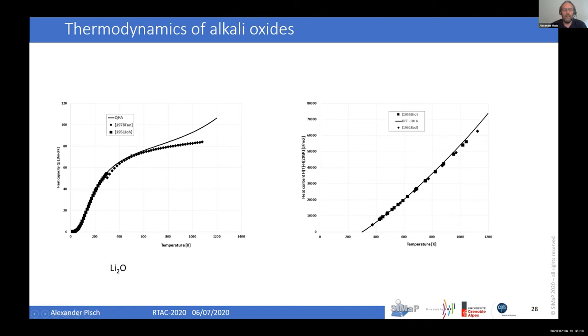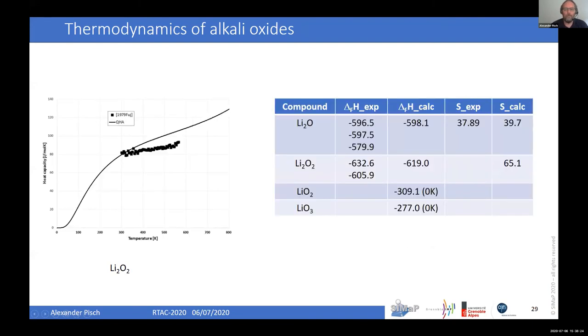So I would say starting from here, it may be better to follow the experimental values. And you can see that here also, if you have heat content, that you start to derive from the heat contents. But overall, the agreement is good.